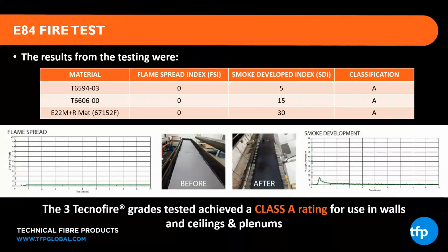So during the test, they're going to run a high heat flux flame from the bottom of the one end of your sample. And there's going to be an open window along the side of the tunnel that a technician will sit and watch to try to see how much of a flame spread is observed in that side of the tunnel. So we actually had a 0 flame spread for all 3 of the Tecnofires tested, meaning it never caught fire on the surface of the material. The after looks like it had, but what you're seeing there is that formation of that char layer. So that char layer that is built up of some high temperature fibers and also the expandable components has done its job properly, and it didn't allow a flame to propagate. Now, what surprised me, the SDI, the smoke develop index, where again, the maximum for this test is 450.